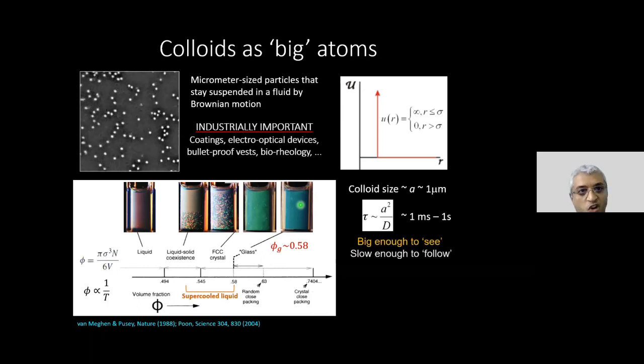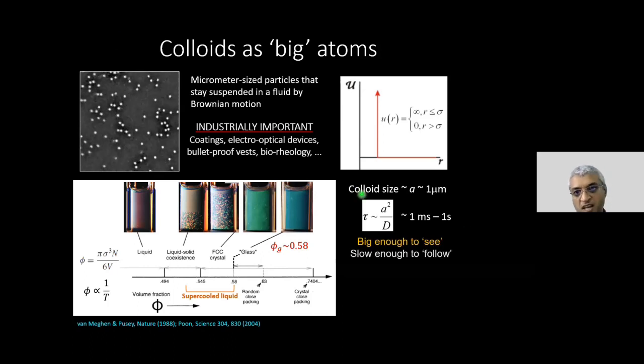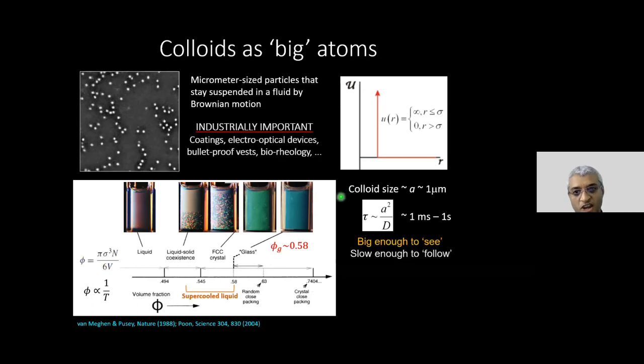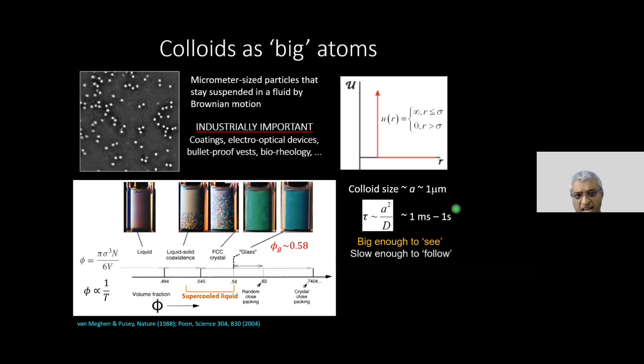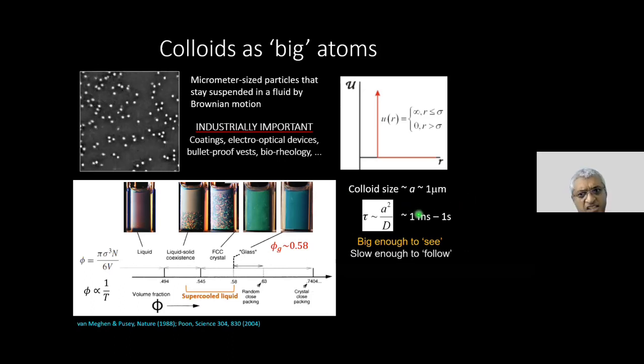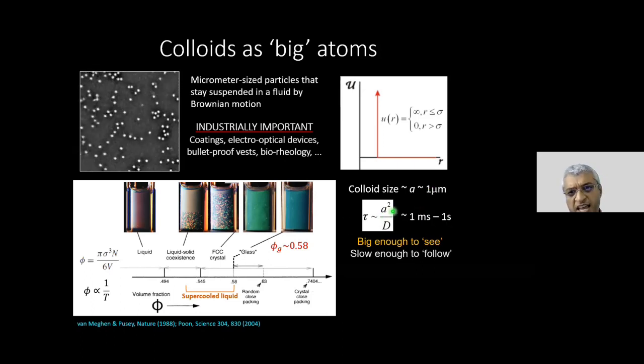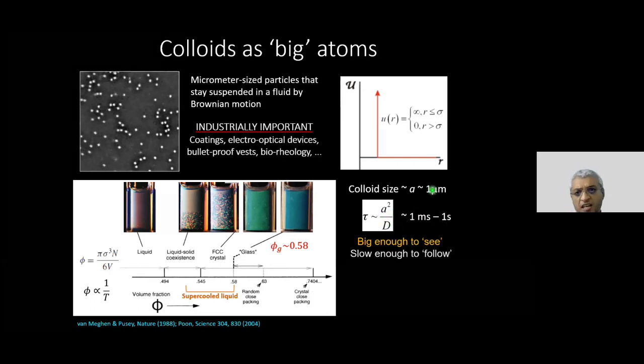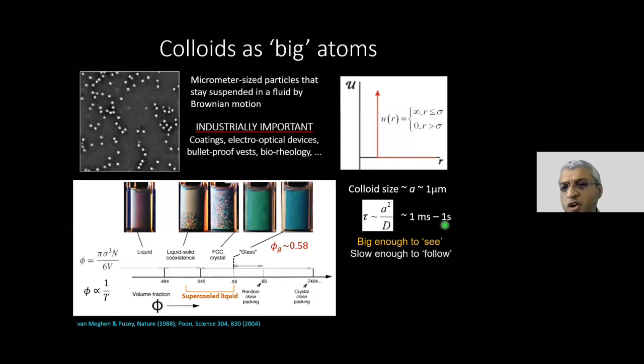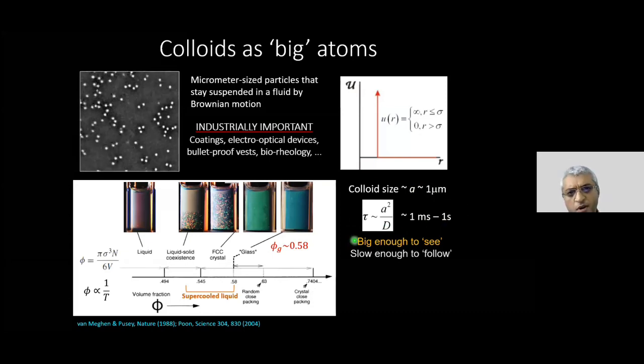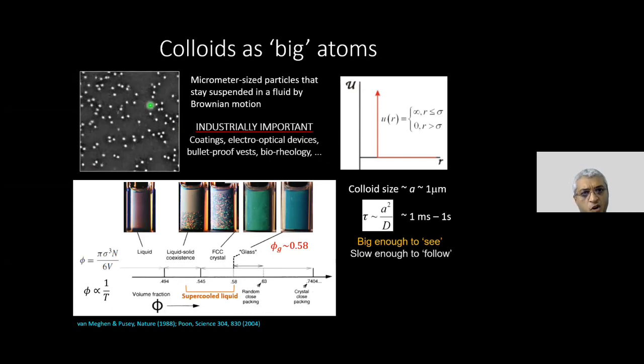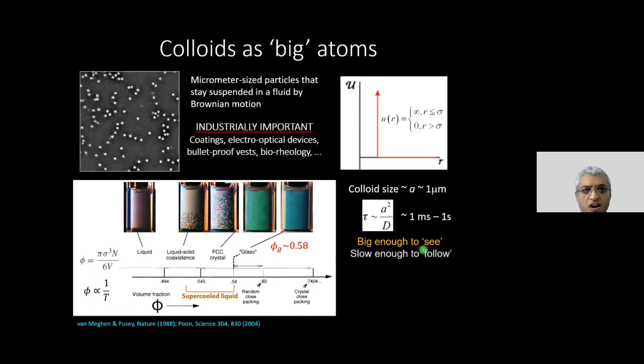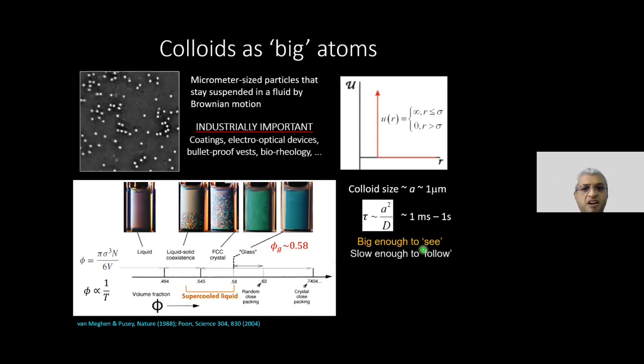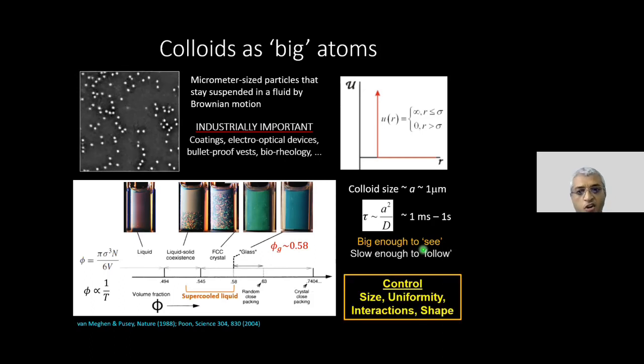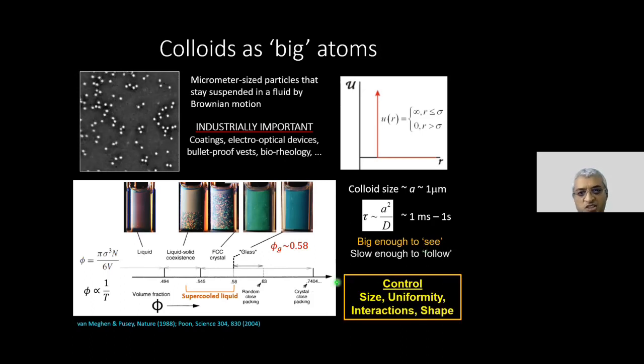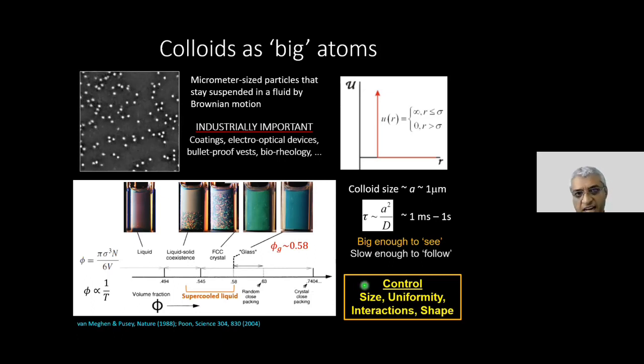But the nice thing about colloids, as is captured by this movie, is that I can see what's going on, right? Because if I take a colloid of about a micron in size, the relaxation time, you can evaluate it. Here, a is the particle size, D is the diffusivity, and it turns out to be between about a millisecond and a second, depending on the viscosity of the fluid, which means that if I have a colloidal suspension, I can see what's going on. I can also follow dynamics as a function of time. And colloids are great because I get to control the size, uniformity, interaction, shape, all of that.